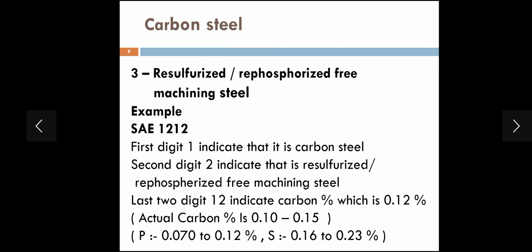So again, as per SAE system, first digit 1, second digit 2 means it's a resulfurized, rephosphorized free machining steel. Last two digits 12 indicate carbon percentage, which is 0.12%. The sulfur percentage in the steel is 0.16 to 0.23. Phosphorus percentage in the steel is 0.07 to 0.12%.